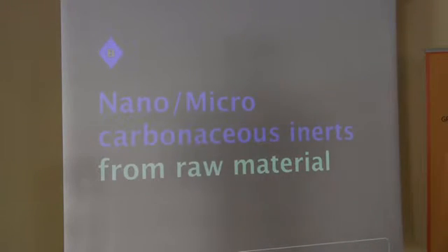The first activity we did regarded adding nano or micro carbonaceous inerts obtained from raw materials. In particular, unfortunately, the light is very low. The raw materials were bagasse fibers, hazelnut shell, peanut shell. We tried, of course, all things organic because we need carbon. We treated these materials, obtained by pyrolysis. By milling, we obtained sizes from millimeter to micro to nano size. We obtained these inerts.